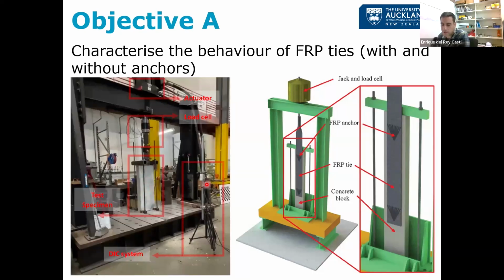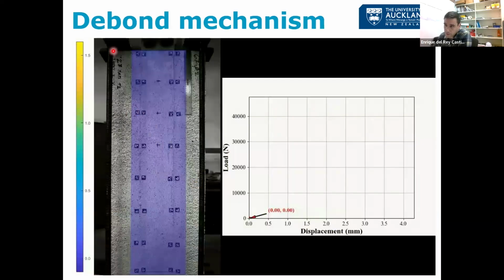So we can use DIC, which is digital image correlation. And basically it's just tracking dots that we paint on the material during the test. So then a software can track those dots in the pictures and translate that to displacement, movements, and from there strains, which is what we have here. This is the block in the back. The FRP is between those two rows of black squares. We are pulling from the top up, and this is the strain gradient. So blue is 0, and as it approaches yellow, it approaches the rupture. So when I click next, hopefully the video will start.